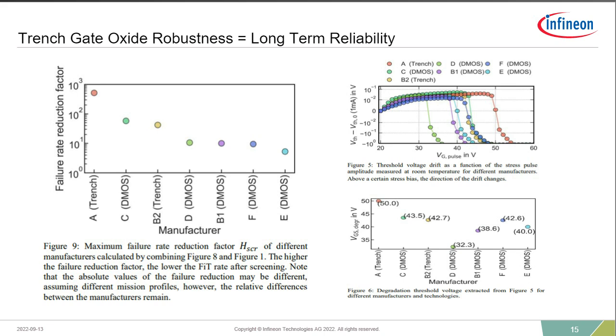And when you see this fall in the line, as an example here with this DMOS-based device, this is when it reaches its dielectric breakdown and the device fails. And you can see here this red-orange color. This is the Infineon devices. And what this shows is that we have a significantly higher or more robust gate oxide structure, and allows the device to be driven up to higher voltages before you start to reach this dielectric breakdown at almost 50 volts.